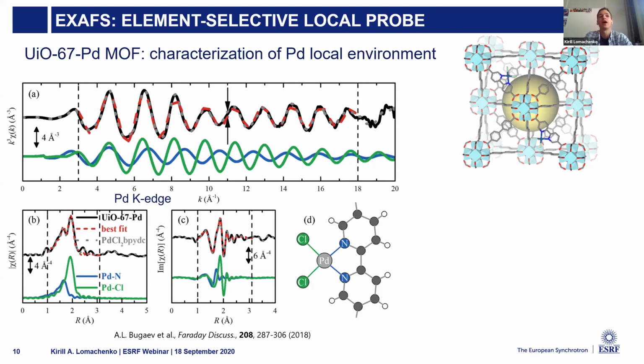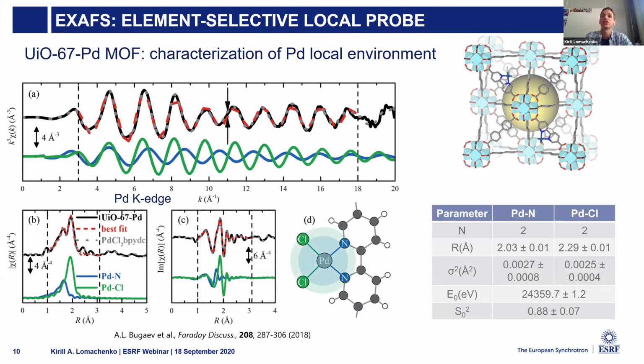When we analyze the data and do the EXAFS fitting, we see that the signal can be very well reproduced by two contributions, palladium-nitrogen and palladium-chlorine, with the coordination numbers and bond distances that can be very precisely determined by EXAFS, so we get precise values of these bond distances and coordination numbers.